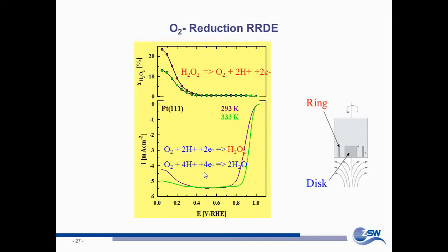We also have an issue, we can't cover it in this lecture series completely. If fuel cells degrade, platinum is dissolved from the cathode, is moving into the electrolyte, and as the potential drops, there's a band of platinum forming in the electrolyte membrane. And at this band of platinum, hydrogen and oxygen meet, and so they are reduced. And since hydrogen is more mobile than oxygen, it will have low potential and it will form peroxide.